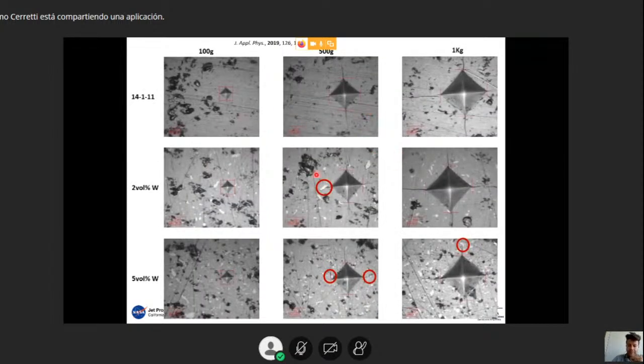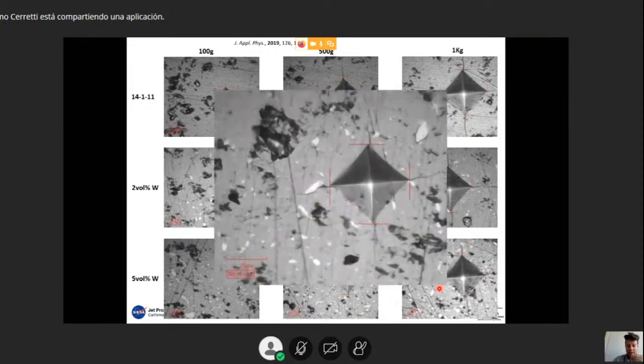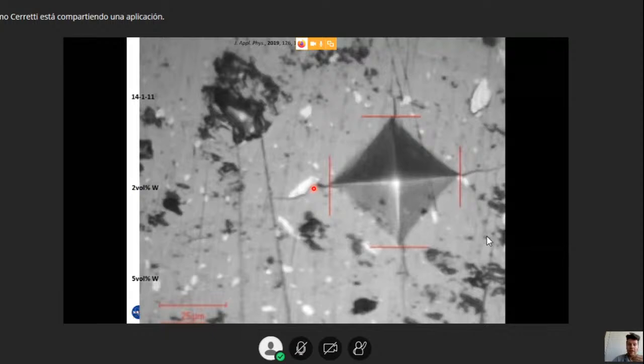These are the images from that, and in the indentation we can see what tungsten is actually doing: it's deviating the cracks that start propagating from the indentation. It's normal to start seeing cracks propagating from there because it's the start of mechanical failure of the material. But it's really important what tungsten is doing. Sometimes it's deviating the cracks. In some others, it's stopping them before they propagate. That is a signal that the material is more